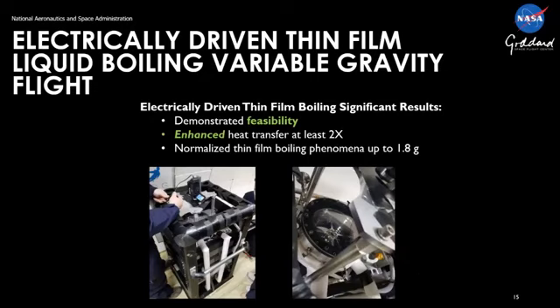So this is the ISS experiment. What we did do is we demonstrated that electrically driven thin film boiling actually is feasible. We showed enhanced heat transfer up to 2 times what you would get in the lab. And then we normalized the thin film boiling phenomena up to 1.8 G. In other words, we were able to have all the heat transfer data from microgravity, 1 G, and 1.8 G fall on top of each other. And I'll show that chart later.